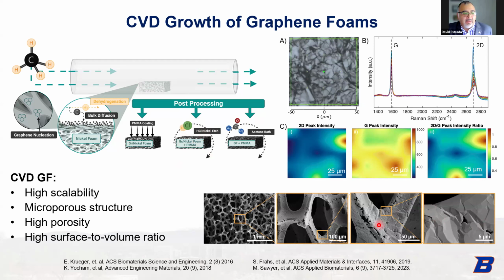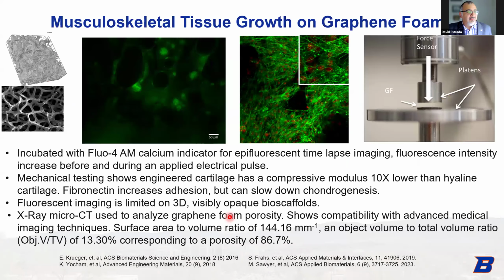Graphitic and graphene foam. The pores here are large. They're on the hundreds of micron scale, which is good for nutrient diffusion into the tissue and waste removal as well. And then the cells are on this electrically conductive scaffold, right? So we've done some work in the past where we were able to seed this foam with C2C12. It's a pluripotent cell line that can go down the muscle and bone pathway, as well as ATDC5s, also a murine line that can go down the chondrogenic pathway. And we characterized the functionality through electrical stimulus and mechanical testing, right?